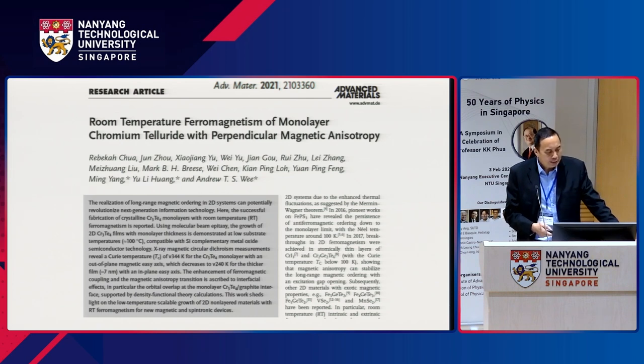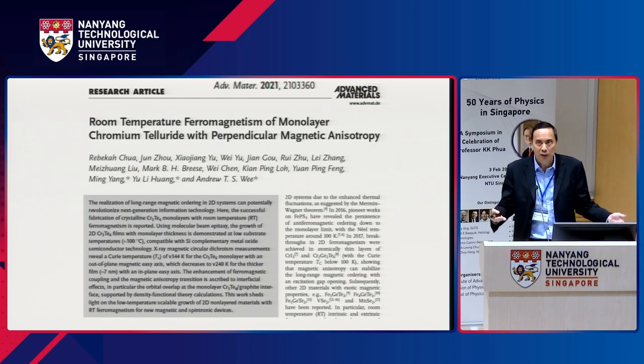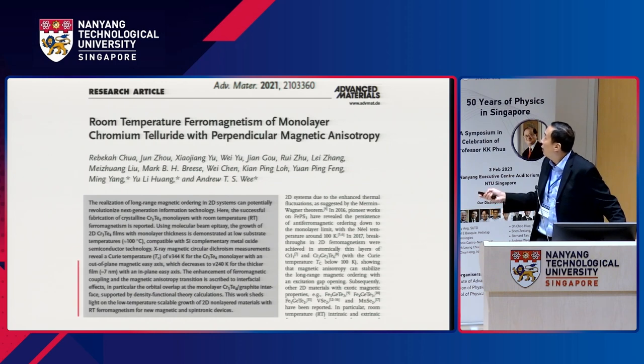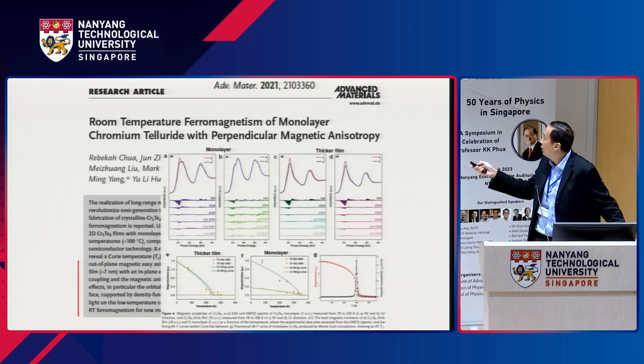Now, we also tried chromium telluride, which is a different material, which is not a layered material, so it was more difficult to grow by MBE. We showed that it had room temperature ferromagnetism with perpendicular magnetic anisotropy. This is important because for magnetic storage devices, it's only useful if you can get the Curie temperature above room temperature. Otherwise, you have to cool your whole computer, which is not convenient. So this is just the XMCD data showing that at the monolayer, you have a higher Curie temperature than the bulk layer.